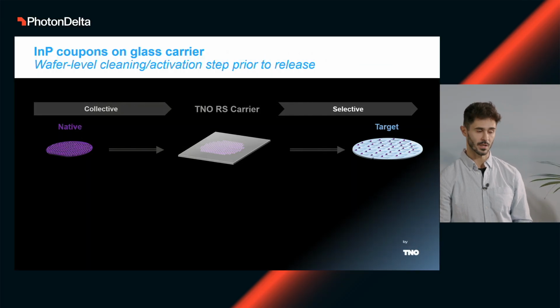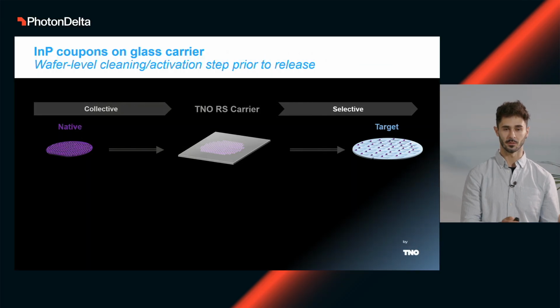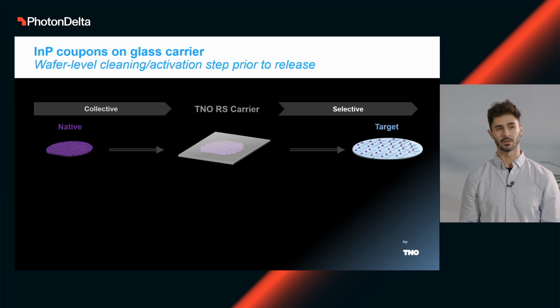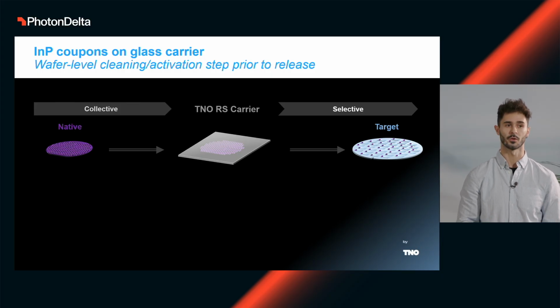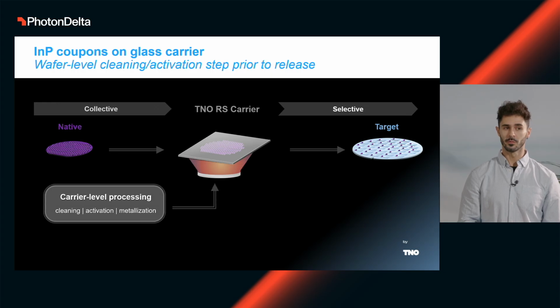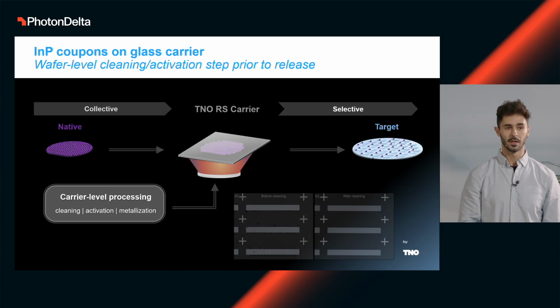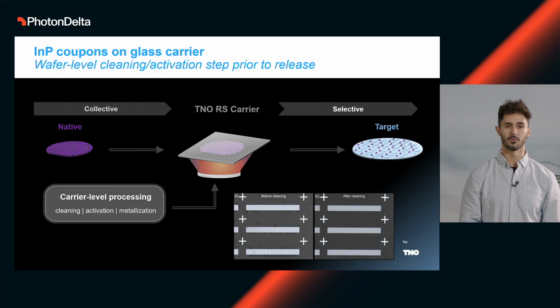One of the key advantages of our technology, and of the fact that you split the pickup from the selective release, is that in between, prior to release, you can do a cleaning and activation step or whatever other processing to your components. This is very important, it's quite unique, and you can do it at the wafer level. So all the components can be treated and activated for a specific type of bonding or specific surface treatment that you want. We notice this when we work, for instance, with coupons technology and tethers: you can completely clean your surface, and that has a strong impact later on when you want to integrate them and keep the pristineness for the coupling.